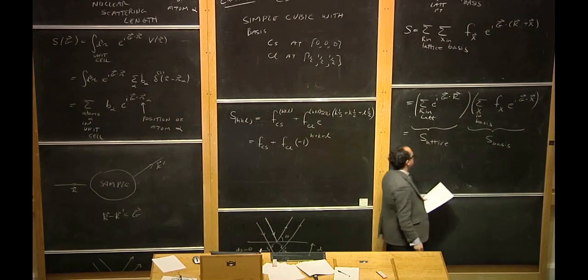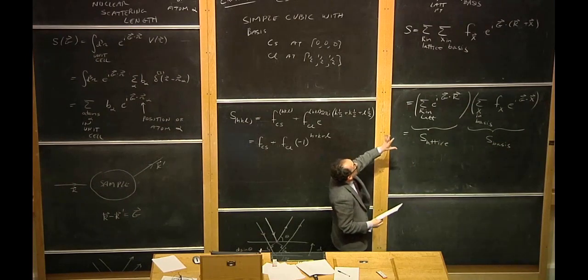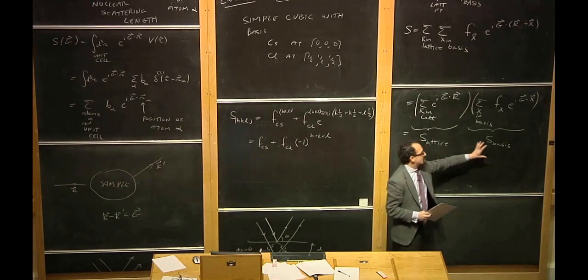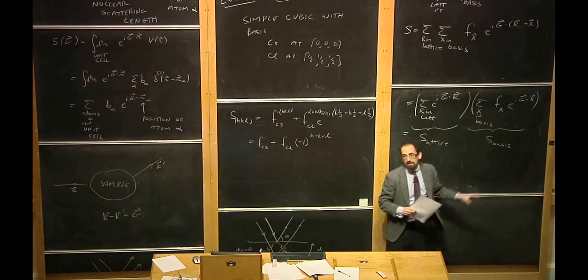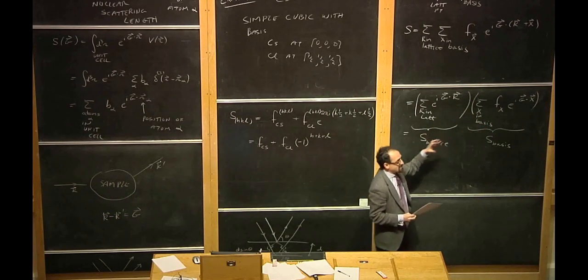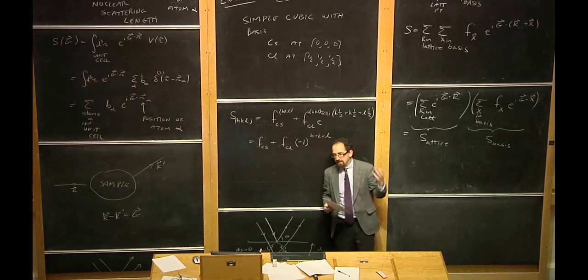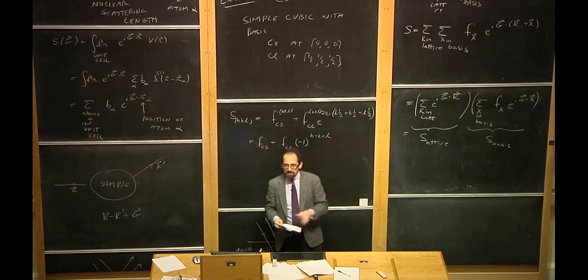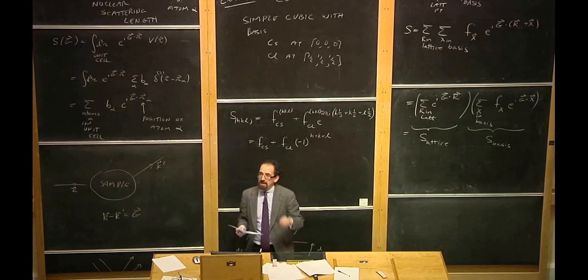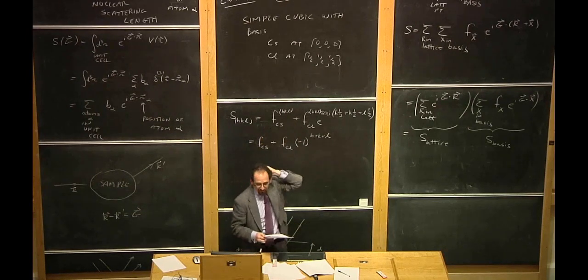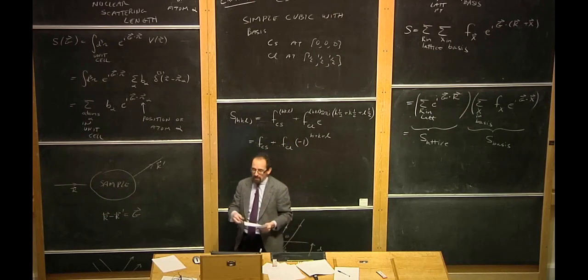So it's really pretty much strictly true that the structure factor for any crystal is the structure factor for the lattice alone times the structure factor, this factor here, for the basis. So if the structure factor for the lattice vanishes, in other words, if you're not satisfying the selection rule for the lattice type, then the whole thing is going to vanish. So it doesn't matter how complicated your basis is. If it's FCC, in order to get scattering, you have to satisfy the FCC scattering rules that H, K, and L have to be all even or all odd.